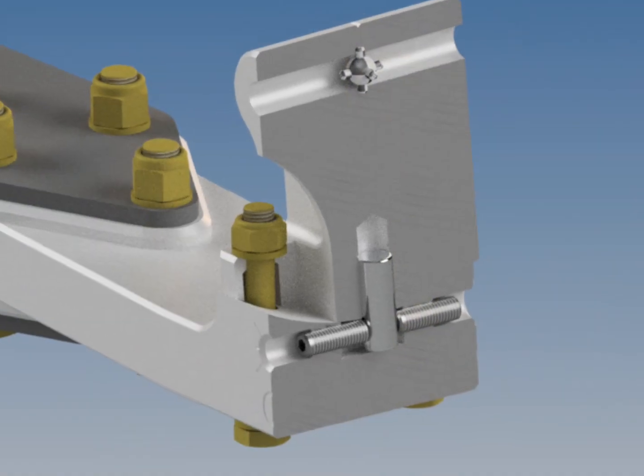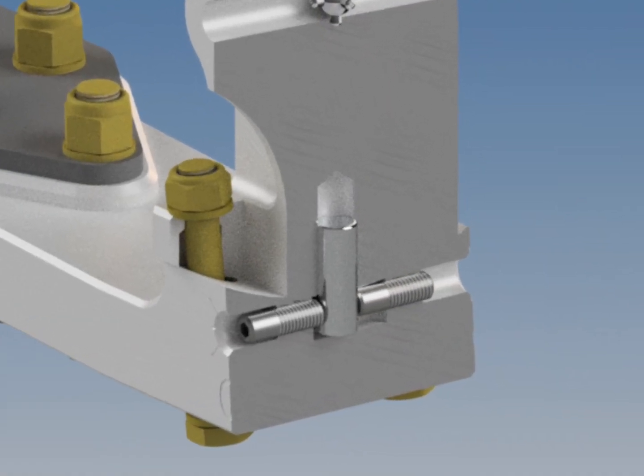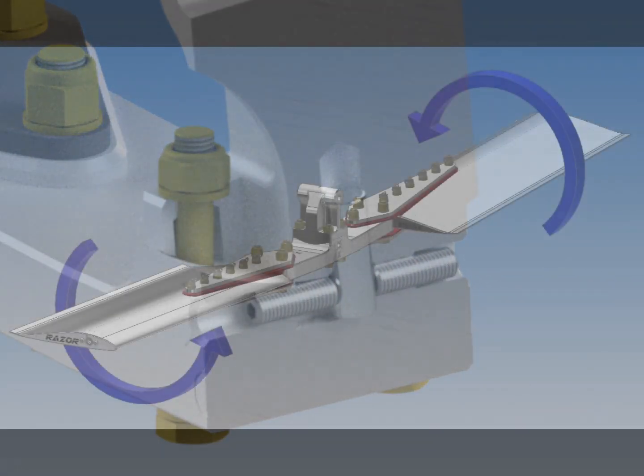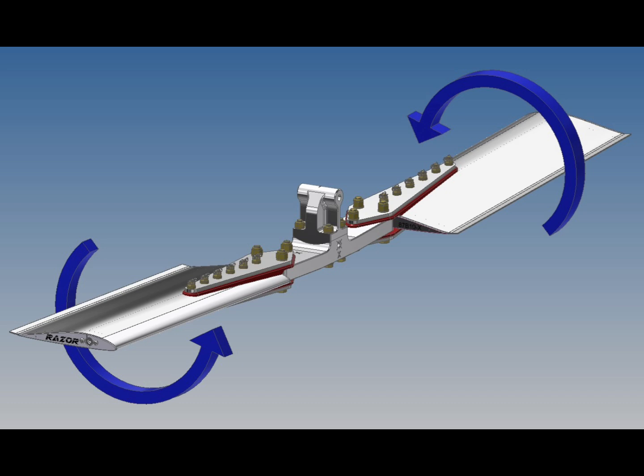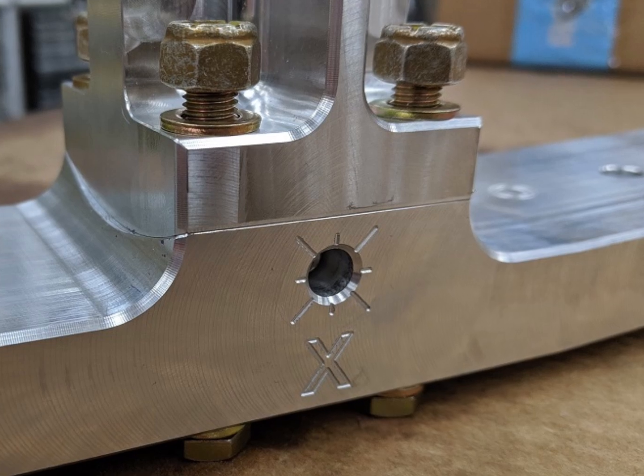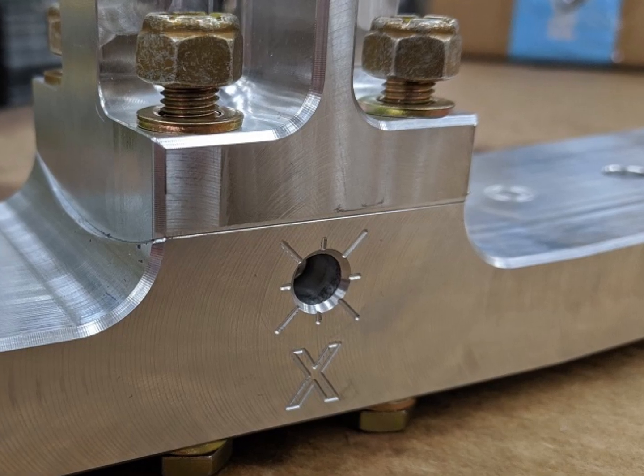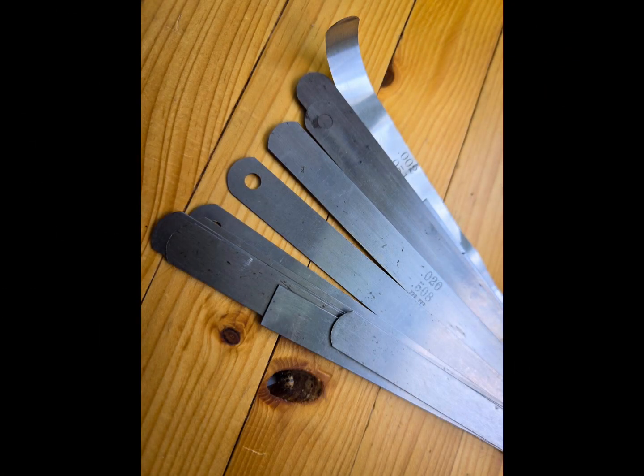Here's an animation showing a much exaggerated motion of how jack screws can push the teeter block back and forth. This will in turn add pitch to one blade while reducing the pitch of the other blade. If you need to increase the pitch or the fly height of the X blade, just simply loosen the bolts a little bit, give the X screw a quarter turn or so, retighten the bolts. Just that simple.